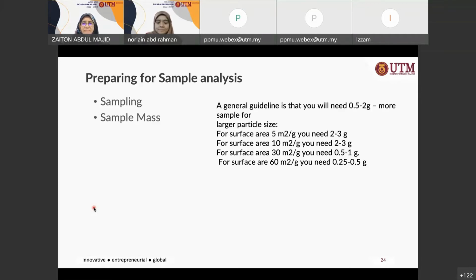Okay, how do you prepare for your sample analysis? Of course you do your sampling. Now remember, the amount of sample you put in for the analysis is not much. How many grams normally? Maybe less than 0.1 gram, 0.5 grams, not much. It depends on your sample also, okay? The sample mass is basically between 0.5 to 2 grams, depending on surface area. If your surface area is about 5 meters squared per gram, you need between 2 to 3 grams and so on. Okay, these are just guidelines which are suggested by some of the instrument suppliers.